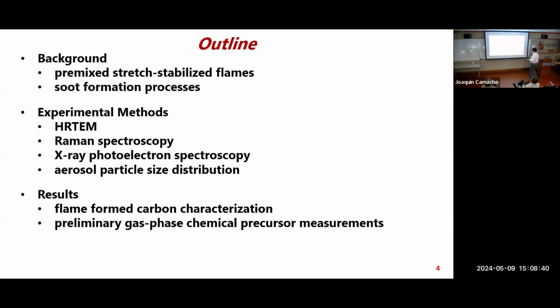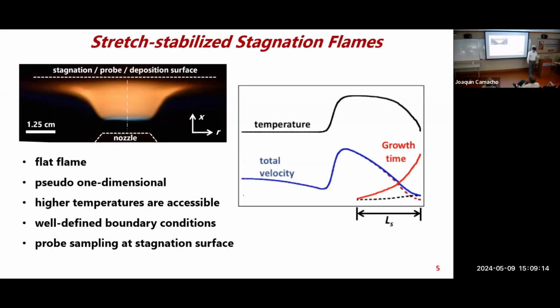Today I'll focus on experimental results showing evidence that indeed we do see a transition: at lower, typical flame temperatures you see soot-like structures, and as you increase the temperature beyond typical flames, you do see graphene-like structures. And where we are now is also trying to go to the steps before soot even forms, the precursor chemistry of the flame that would lead to solid particles, focusing on this regime of high temperatures.